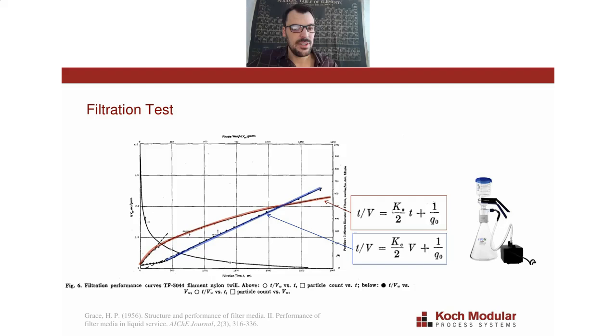Very common to see this in polymers and other soft solids, viscose rayon, celluloses. The cake is compressing, or the pores between the particles are collapsing, and the resistance of the cake is changing with time. If you contrast that with the blue curve, the resistance of the cake is not changing with time, it's only changing with cake thickness. The cake is sturdier, the pores are not collapsing, and so the only issue you have to contend with is a cake that's twice as thick has twice as much resistance as a cake that's half as thick.